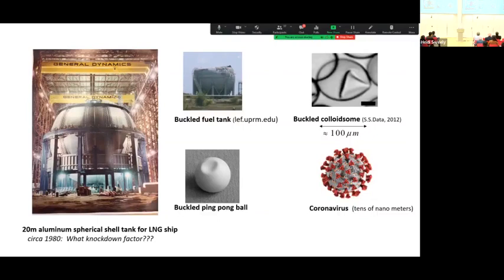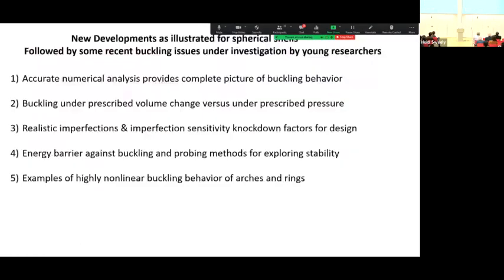By the way, in the late 70s, I did consulting work for General Dynamics. And so this is a tank for one of these liquid natural gas tankers, which are very much in the news these days for obvious reasons. And you've probably seen these ships. They typically have 4 or 5 of these gigantic spherical tanks. They're made out of aluminum, and that's because, for the material scientists in the crowd, it's a cryogenic cargo. You don't want to use steel, probably. It's not obvious, but the reason I was a consultant is that the thickness of the shell has to be designed so that it doesn't buckle. So the question is, for this type of loading, what was the knockdown factor? That's the role I played in coming up with one.